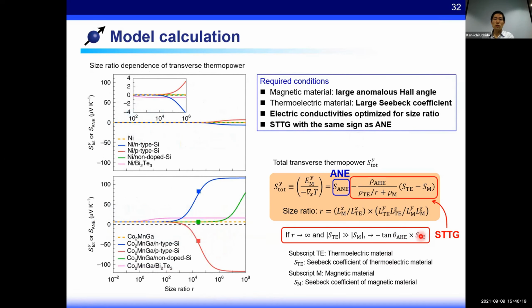Here we plot the total transverse thermopower as a function of the size ratio for the typical combinations of the thermoelectric and magnetic materials. When the anomalous Hall angle of the magnetic layer is large, here we assumed Co2MnGa, the STTG contribution can be much greater than the anomalous Nernst contribution, and its sign can be reversed when the sign of the Seebeck coefficient of the thermoelectric layer is reversed.